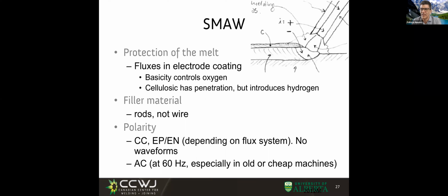The comment is that cellulosic electrodes need a certain amount of moisture, and this is a practical comment. Otherwise, the coating can crack off and give an erratic arc. And this is an interesting and important comment because, well, you can have these electrodes wet.